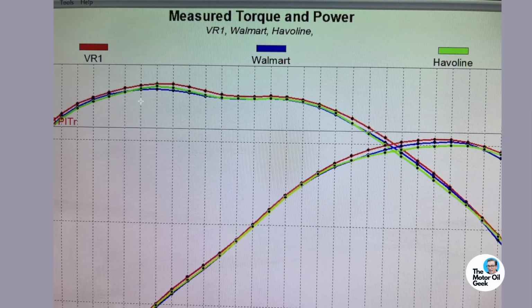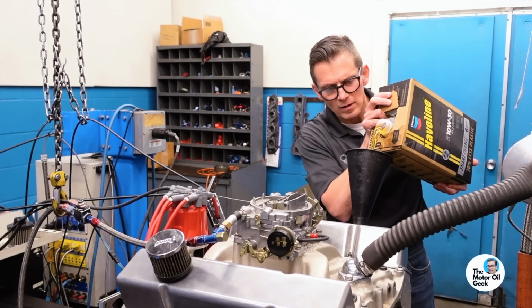So the oil that actually made the most horsepower was the Valvoline VR1, and it also was running the coolest. And that's not a coincidence. Anytime you're reducing friction, you're going to be reducing operating temperature. And again, we've seen this time and time again, especially with this engine. When you reduce friction, not only will it show more power, it will also show less temperature, because friction is temperature. Great correlation here again.